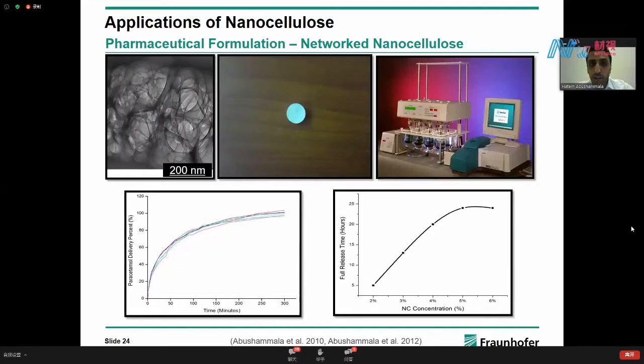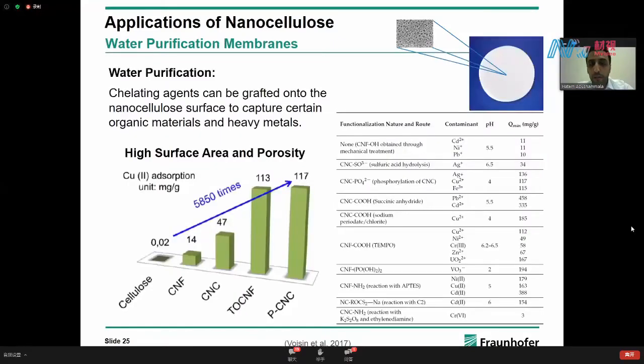Nanocellulose is also interesting for water purification due to the very high surface area and porosity, and also because nanocellulose can be functionalized with whatever kind of chelating agent you want, so you can make selective membranes to purify water from certain contaminants. And here you can see in this figure how efficient cellulose nanofibers and cellulose nanocrystals, without any modification, are in capturing copper compared to cellulose.